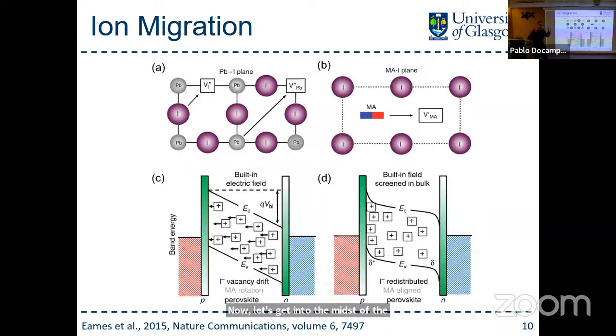So they're semiconductors, but they're also ionic conductors. What that means is that we've got lots of vacancies. When we crystallize, this is a solution process, it crystallizes very quickly, and there's always defects when it crystallizes. The defects don't play a role electronically, but there's still atoms missing in the lattice. Those are the ionic defects that we're going to be talking about for the next 20 or so minutes. Now, there are three possible defects. You can have the lead moving, you can have the halide moving, or you can have the organic cation moving.